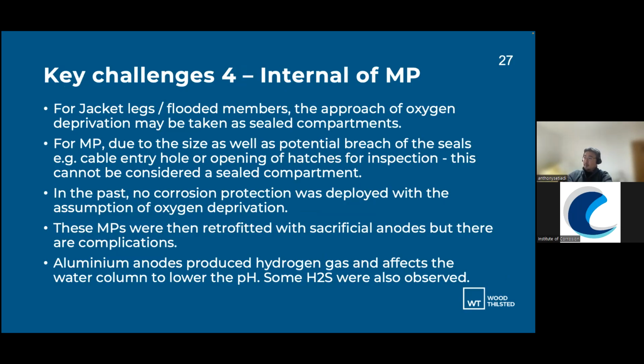Challenge 4 is probably one of the more challenging things that I've seen in offshore wind. Previously, for the internal of the monopile, the approach from DNV is to say for flooded members we can use oxygen deprivation. Due to the size of these monopiles and the size of water that's in there, and there's always potential of breach of the seals, e.g. cable entry holes, because we do have cable entry zones whereby the cables from the outside need to go on the inside of the monopile. It's not considered that it's oxygen free, and therefore there is always replenishment of oxygen and water inside, which means corrosion occurs, and we've seen that in the past.